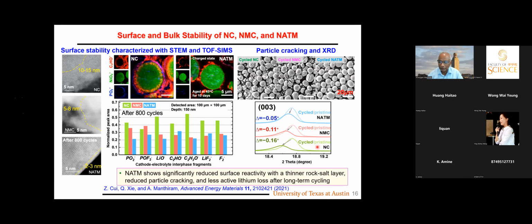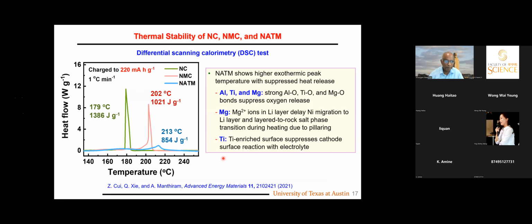So if you see here NC, there is a big difference in the location of the 003 peak. That means there is a loss of more active lithium in this case, medium loss, here the least loss. So clearly, a lot of active lithium is consumed in the CEI formation, and that's why the cyclability is fading. This is safety or thermal stability.